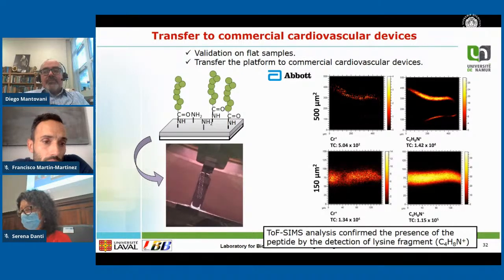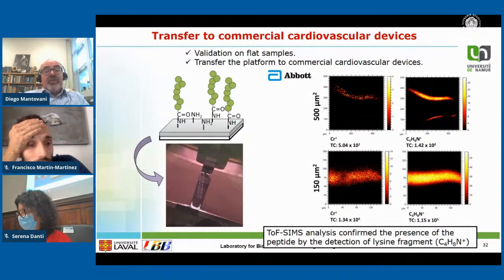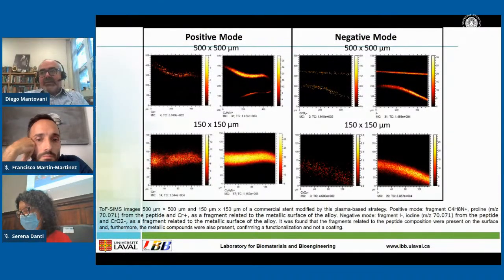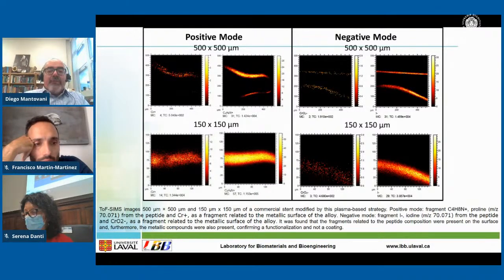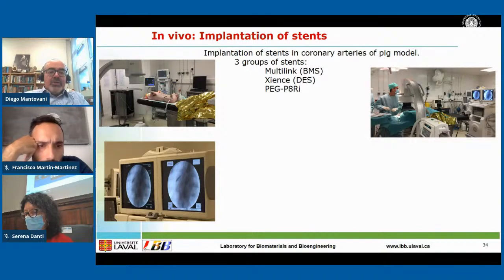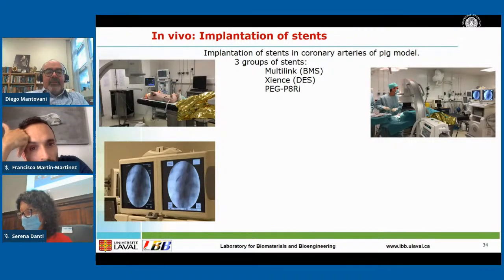TOF-SIMS imaging is not something easy to carry out, even on flat surfaces, but imagine here on 80 micron structures. This is a positive and negative mode TOF-SIMS imaging of a commercial stent modified by the plasma-based strategy, and you can see in general how clear the yellow segment shows the presence of the peptide. And then we went in vivo, in a pig model, and we compared 3 stents. Multilink, which is a bare metal stent, nothing attached. Xience, which is a drug-eluting stent coated with fluorocarbon and grafted with sirolimus, and finally a PEG P8RI stent.